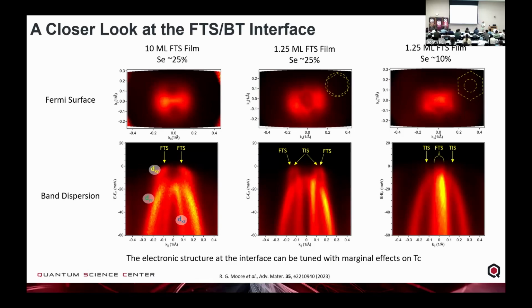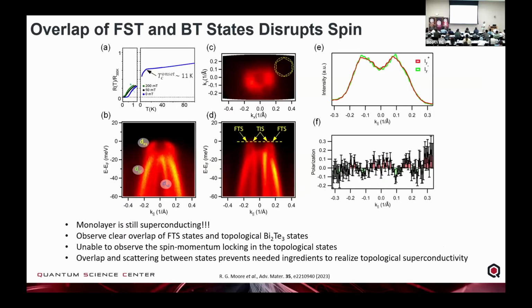And so here, in the monolayer limit, we can actually see the superconducting states and these topological states. And we can see how the electronic structure changes as we change the doping of the material. Now, even down to the monolayer limit, we see that this thing is still superconducting. A single unit cell thick iron tellurium selenium film is still superconducting.